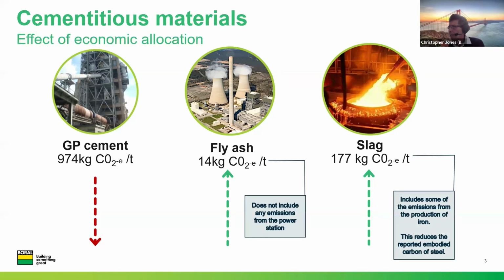Firstly, we need to understand how these values are determined. One of the reasons why slag is higher in embodied carbon than fly ash is that it does require some processing. It has to be granulated and then milled into a powder. But it also gains some embodied carbon through the process of economic allocation.